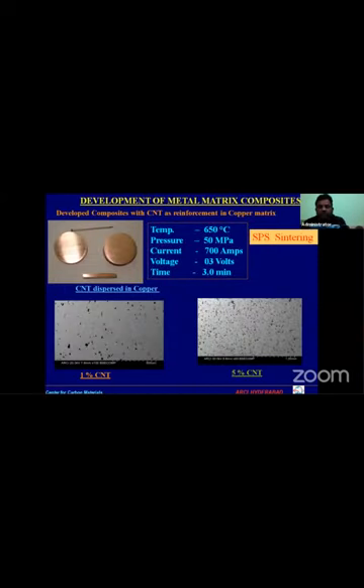Now, we have also made some metallic composites by dispersing carbon nanotubes. SPS, spark plasma sintering, was used, where the total time was hardly 3 minutes. So in 3 minutes it was sintered in copper at a temperature of 650, and you can get 1% CNT and 5% CNT so uniformly dispersed, and the properties were measured. The hardness increased very high. Even the electrical conductivity also improved by dispersing the carbon nanotubes into the metal.